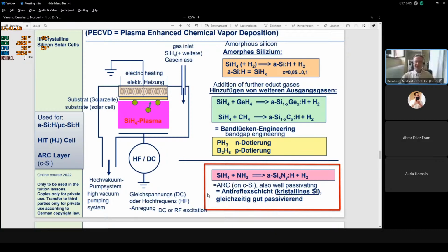The process I want to concentrate on is here on the top right, red framed, where you use the gases silane and ammonia. And in this plasma, a reaction is triggered which leads to the deposition of an amorphous silicon nitride layer, which also contains some amount of hydrogen, which is also important. This amorphous hydrogenated silicon nitride layer is firstly the antireflective layer, and secondly, it's the passivating layer.